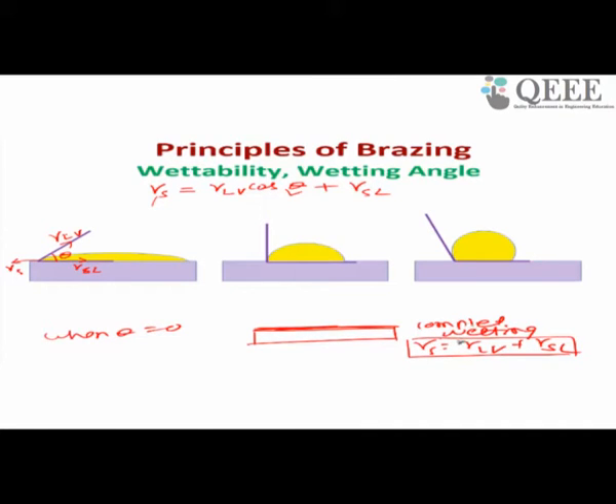This equation tells us that if you want to select a filler material for wetting a solid surface, you have to select it in such a way that the surface energy of the filler material should be sufficiently lower than that of the solid material. It means the surface energy of the solid material should be much higher than that of the filler material. Okay. Now what happens when theta equals 0?